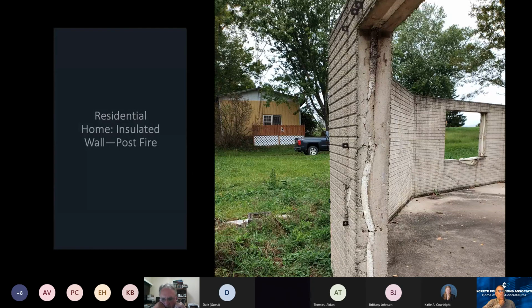This is an above grade concrete home. This is an old home. This one was done in the 60s. You can see the insulation. The homeowner called me. It had a fire, burned everything down but the concrete wall. And they called me and said, hey, we're really concerned about some cracks that we're seeing here on the outsides of these walls. I had to laugh because you can see, I mean, the cracks are created because the wall thickness changes.